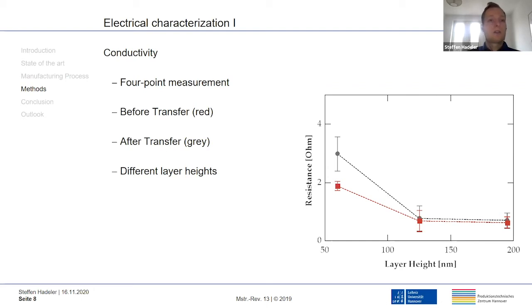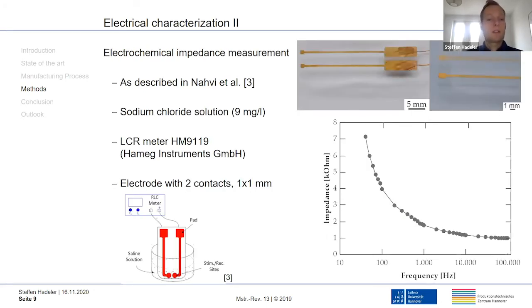After the examination of the conductivity, an electrochemical impedance measurement was performed as described in Nahvi's publication. The test was performed in a sodium chloride solution with an LCR meter. For this purpose, an electrode consisting of 2 electrode contacts with a dimension of 1 millimeter was manufactured, which can be seen in the illustration on the right. We can also see the impedance over frequency on the right, which shows the typical form of these curves.